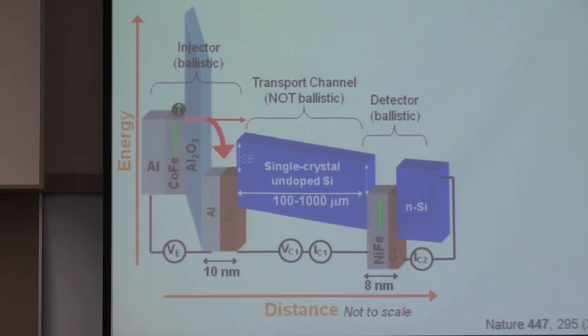The Schottky barrier here, this discontinuity between the conduction band level and the Fermi level, which is normally rectifying and keeps all of these thermalized electrons out of the semiconductor, is here used as an energy filter. It actually enables us to separate the electrons which are injected from the ferromagnet, the ones that are spin polarized, from the electrons that are below the Fermi energy, which are not. Okay?